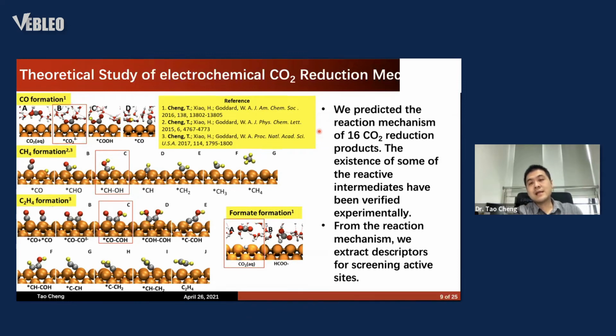Especially when we develop this technique, we can have these accurate predictions. So here I show the cases. The common products from CO2 reduction: the CO formation, the CH4 formation, C2H4 formation, the formate formation. And we systematically investigated and proposed the reaction mechanism from our virtual half-cell simulation. And then we can identify an important reactive intermediate in this pathway. So now we can give suggestions to experiment to improve the catalysts to have better performance.